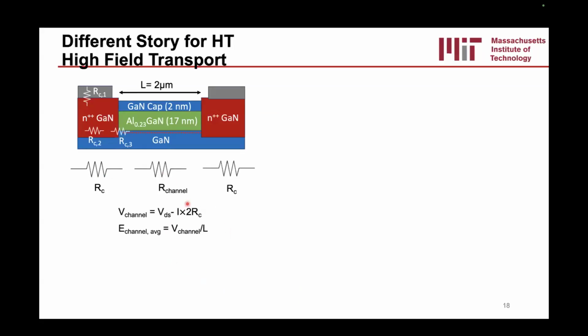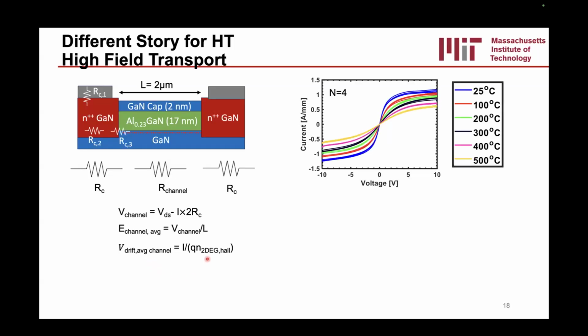We can take into account the IR drop of the contacts, because we know the contact resistance, which we measure as a function of temperature. And so we can actually get the voltage drop across the channel. And we can calculate an average electric field across the channel since we know the length of this TLM structure. Additionally, we can measure the current of the TLM structure. And since we know the 2D density from the Hall measurements, we can actually get the average drift velocity in the channel. And so that's what we do.